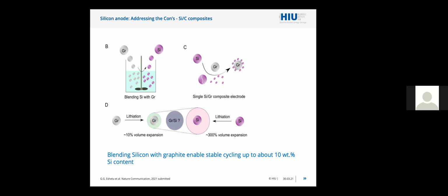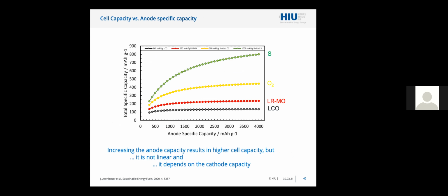And actually, this is more than enough, because we should never forget that it is not that useful to enormously increase the specific capacity of one electrode if the capacity of the other electrode is very low. So if you're looking at this graph, for example, here, you see that the increased anode specific capacity does not really result in an increased cell capacity when you use, for example, a low capacity cathode like lithium cobalt oxide. But obviously, the more you increase the capacity of the cathode, these are theoretical estimations here for oxygen and sulfur, the more you also benefit from the increased capacity of the anode side.